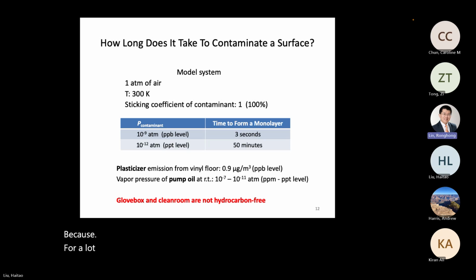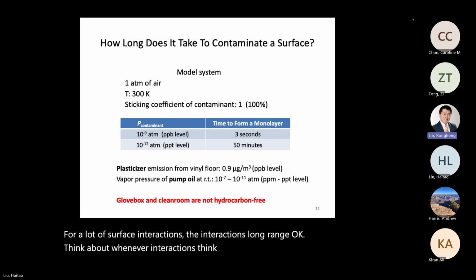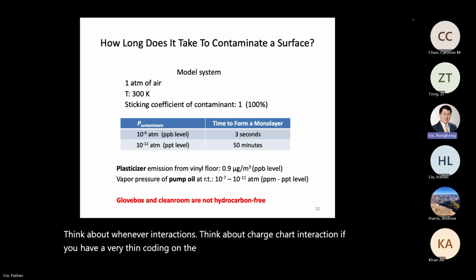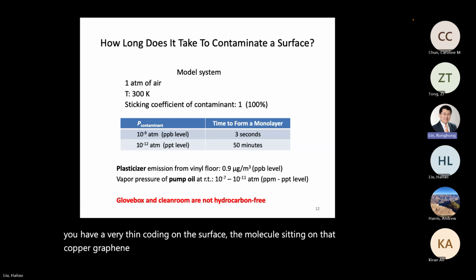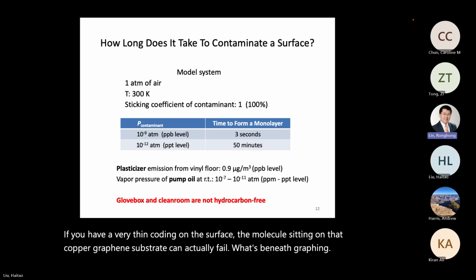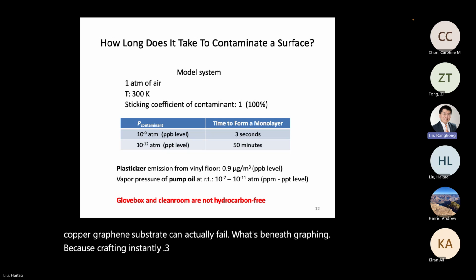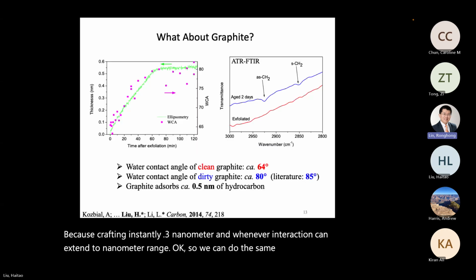because for a lot of surface interactions, the interaction is long range. Think about van der Waals interaction. Think about charge-charge interaction. If you have a very thin coating on the surface, the molecule sitting on that copper graphene substrate can actually feel what's beneath graphene, because graphene is only 0.3 nanometer, and van der Waals interaction can extend to nanometer range. Okay, so we can do the same experiment on graphite.